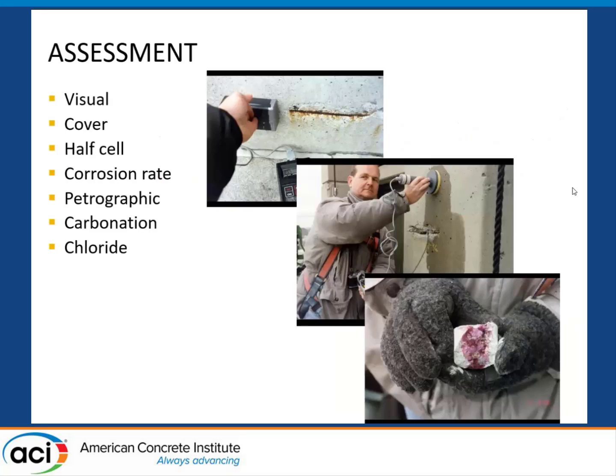The assessment, I think, ties in very nicely with what Pericles talked about. And I think Simpson Gumpertz & Heger did an excellent job with the assessment, very comprehensive. They did a lot of the standard tests that are typically done in reinforced concrete repair. All of this was done in an effort to identify the problems, identify the extent of those problems, and understand the root cause before going on to specify the solution. The photos, starting in the top left, show testing for cover meter for the cover concrete and the reinforcing depth. The middle photo is a half-cell potential test. And in the bottom right is a core that was extracted and tested with phenolphthalein to determine pH levels and carbonation.